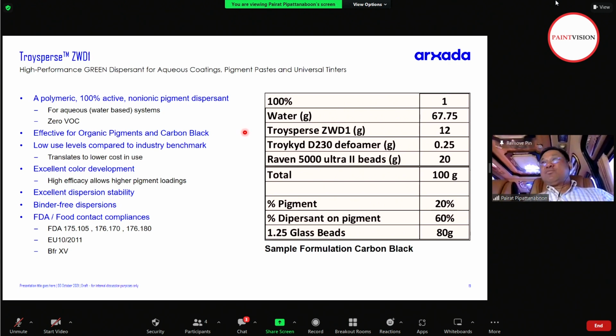The pigment that it works very well with is carbon black, right? Like I said before, FW200 from Orion, the Birla Raven 5000, and also Cabot Monarch 1300, 1400 for this high surface area carbon black.